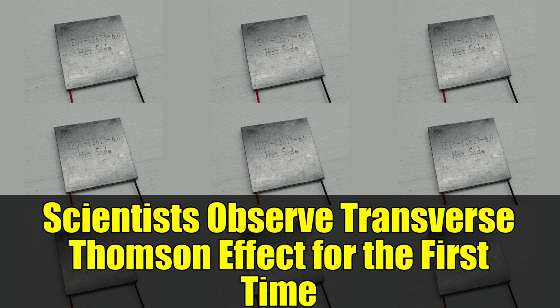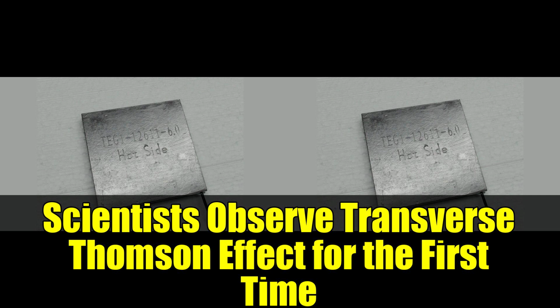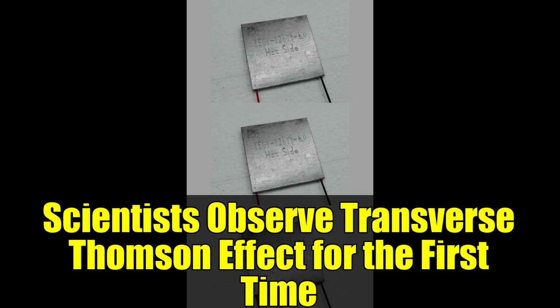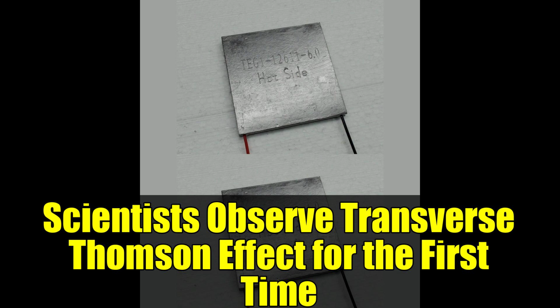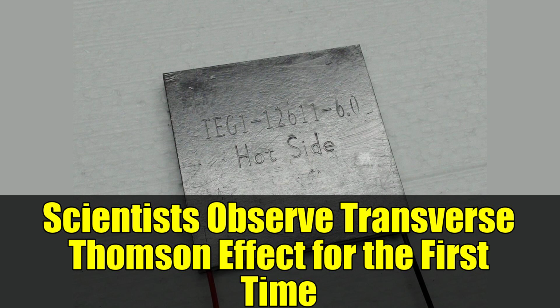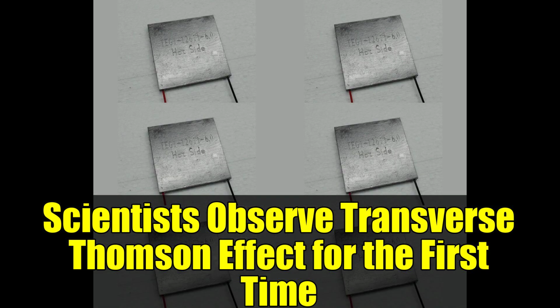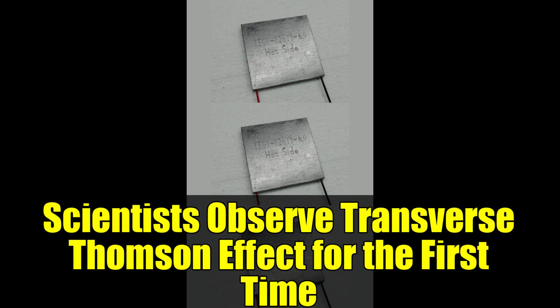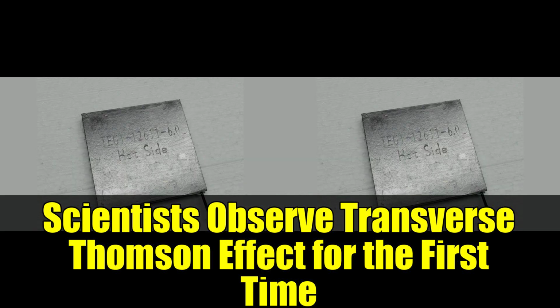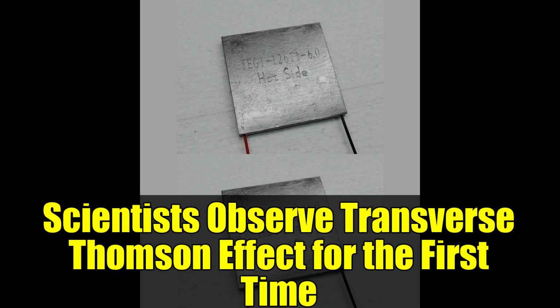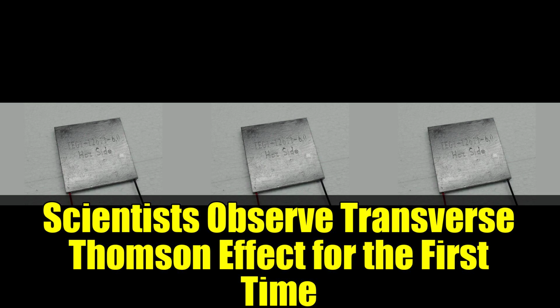The turning point came when the team recognized that the spatial distribution of the Transverse Thomson effect differed from other competing effects. They performed measurements under two conditions, with and without a temperature gradient. By subtracting the results, they successfully isolated the pure Transverse Thomson signal. The first measurement captured both the Transverse Thomson effect and the Ettingshausen effects, while the second measurement, without the temperature gradient, captured just the latter. Subtracting the second from the first yielded the isolated Transverse Thomson effect.